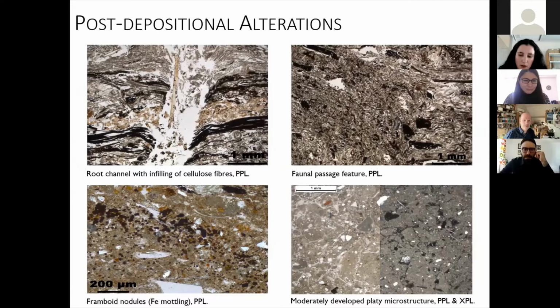Iron features occur mainly in the form of nodules within the matrix of building plasters, sometimes representing inherited features that form in natural sediment from which the architectural materials were manufactured. Frost features, of which we have very, very few examples at Çatalhöyük, were detected in a suspected collapsed roof sequence, and they consist of poorly to moderately developed platy microstructures that are produced by temperature-driven desiccation caused by frost, which can open shrinking fissures in deposits below the surface, and in this case confirm our hypothesis of these being actually roof plasters.